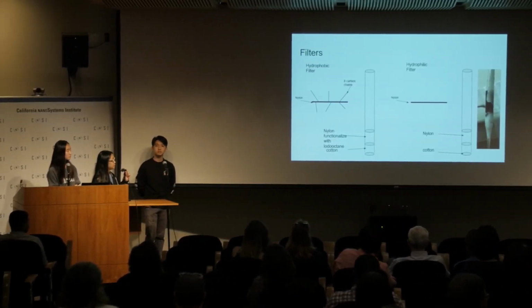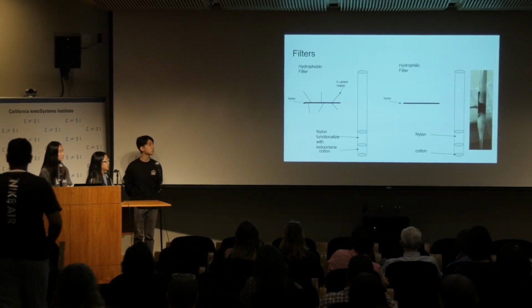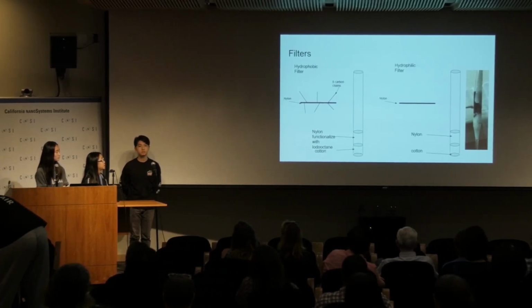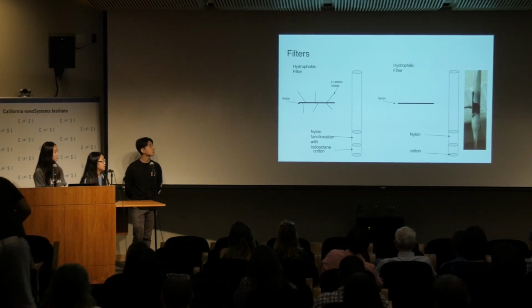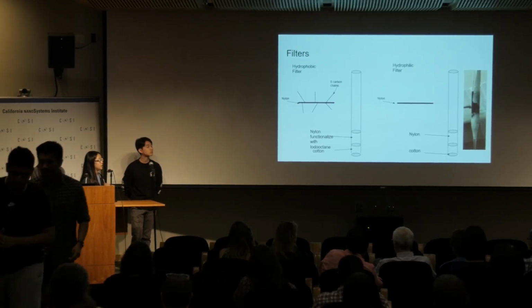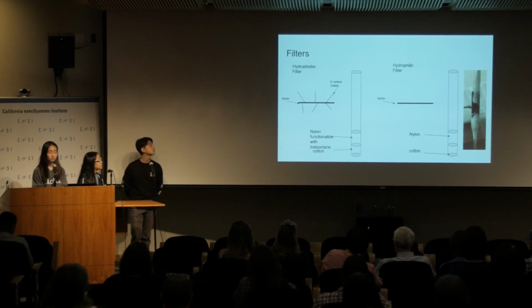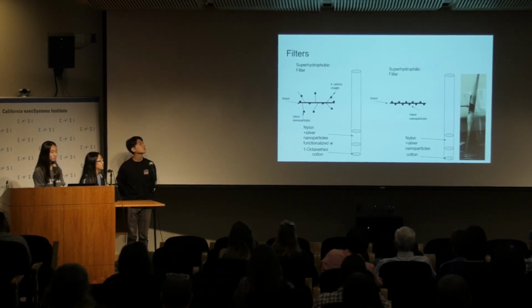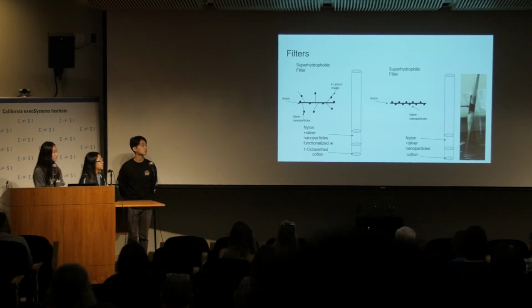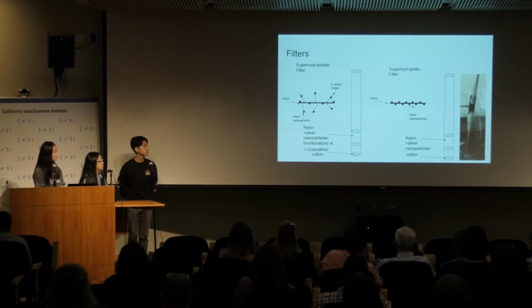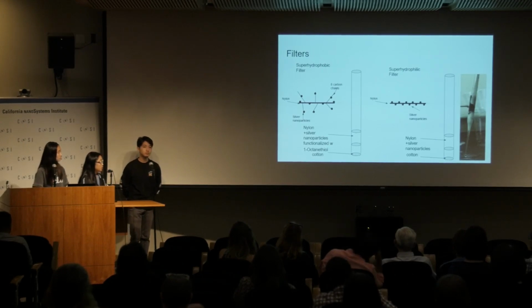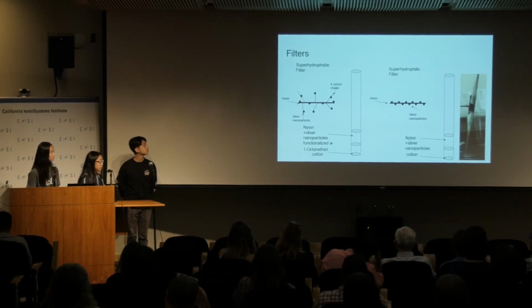So for the hydrophobic filter, it was cotton to keep the nylon filter in place, and we functionalized the nylon with iodooctane to make it nonpolar, making it hydrophobic. And for the hydrophilic filter, it was just cotton with nylon, and because nylon is hydrophilic, we didn't have to do anything else to it. For the superhydrophobic filter, it was the cotton, and then we functionalized nylon with the 1-octanethiol, and we soaked it in silver nanoparticles to give it the superhydrophobic property. And for the superhydrophilic filter, we did nylon and soaked it in silver nanoparticles to increase the surface area to make it superhydrophilic.